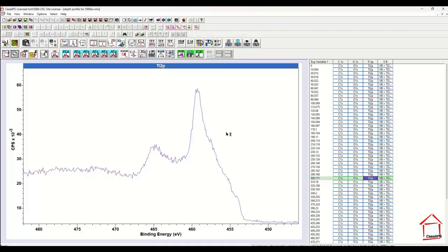An analysis of data of this form would typically be performed in XPS by constructing a peak model, mostly from bell-shaped curves, and then fitting the curves to data, and the arrangement of the curves ought to give us some indication of the different chemical states. Now, to make valid assertions about the chemical state of a structure like this based on a peak model is quite difficult. We could fit these quite easily with a range of different peak models and therefore claim that we had metal, suboxides, all the way through to the titanium 4+.